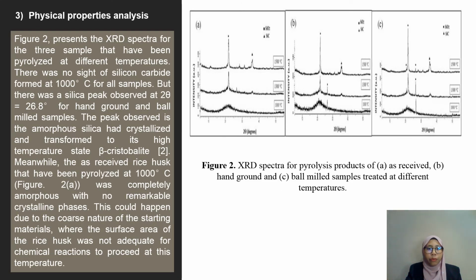The third literature review is physical properties analysis. Figure 2 presents the XRD spectra for the three samples that have been pyrolyzed at different temperatures. There was no sign of silicon carbide formed at 1000 degrees Celsius for all samples, but there was a silica peak observed at 2θ equal to 26.8 degrees for hand ground and ball milled samples. The peak observed is the amorphous silica that crystallized and transformed to its high temperature state, beta cristobalite.